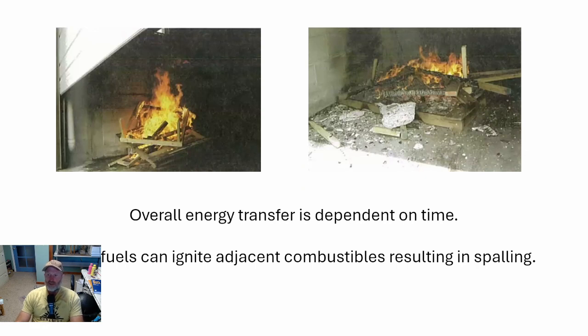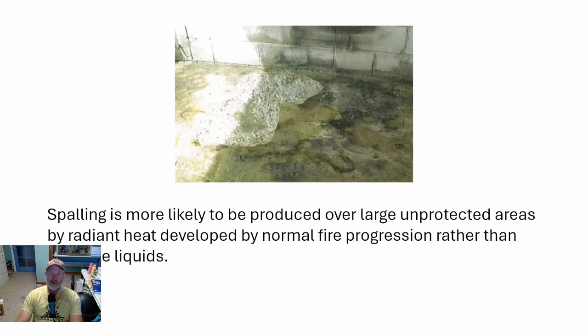Overall energy transfer is dependent on time. It's not necessarily the temperature at a given point. It's the rate of heat transfer from that temperature over time. So liquid fuels can ignite adjacent combustibles. In this case, you see some wood ignited on concrete. That wood continues to burn much longer than your ignitable liquid, and that's what results in spalling. So here's an example from the former images that show the spalling under that wood. Spalling is likely to be produced over large, unprotected areas by radiant heat developed by normal fire propagation rather than ignitable liquids.